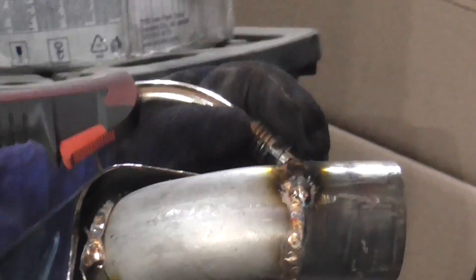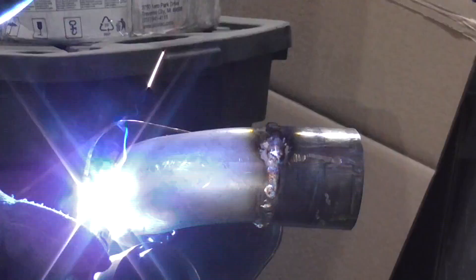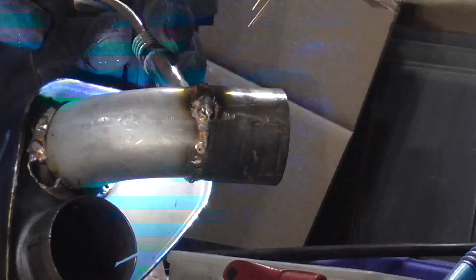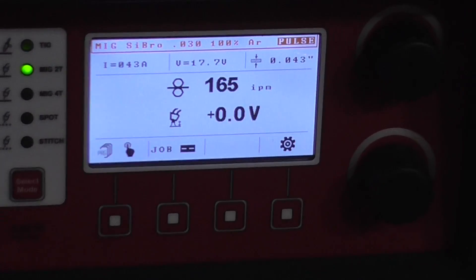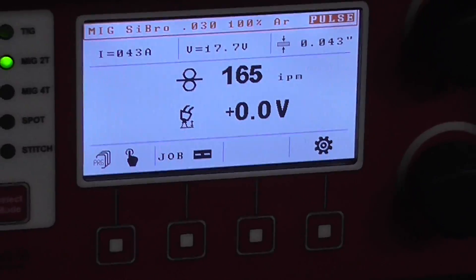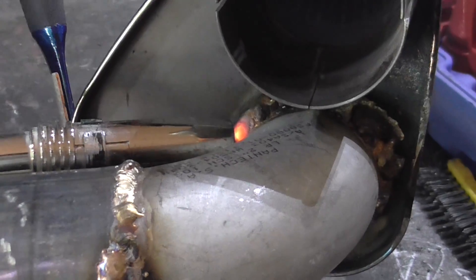This is also highly sped up. I really take my time between tacks and let it all cool down. I have a 10 second post-flow and pre-flow on some parts, so I'm always in an argon-shielded atmosphere. I have my amperage set way down to 43 amps to weld this, and as I make those tacks nothing further cracks on me and it's turning out all right.